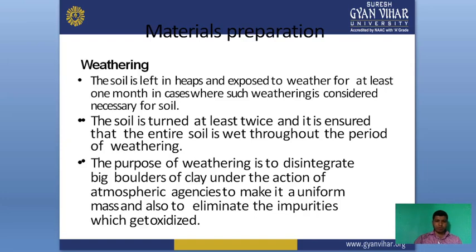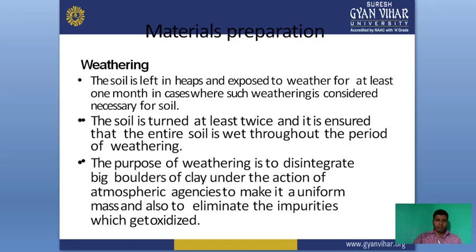Weathering is done for at least one month where necessary. The soil is turned at least twice and it is ensured that the entire soil is wet throughout the period of weathering. The purpose of weathering is to disintegrate big boulders of clay under atmospheric action, making it a uniform mass and eliminating impurities which get oxidized. After cleaning the clay, it is kept for weathering in a suitable place with good atmospheric exposure.